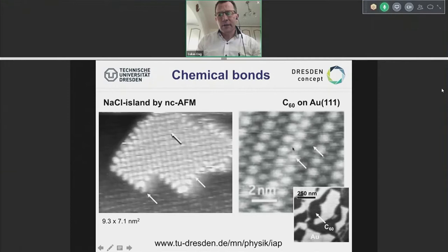Now we found out that these C60, when they are bright, lying on the gold, this is bare gold 111, a good sample, actually lie on the five-fold surface. You know, C60 has 12 five-fold and 20 six-fold surfaces. Here they lie on their five-fold surfaces, while on the other side here they lie on the six-fold surface. And this is reflected exactly in the chemical bonding strengths to the AFM tip. Interesting. So we see that chemical bonds can directly be reflected with a simple scan on the surface.